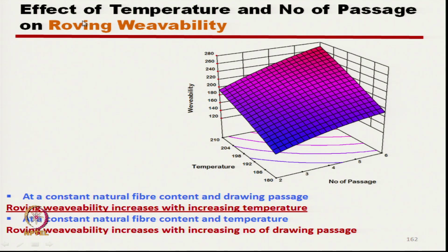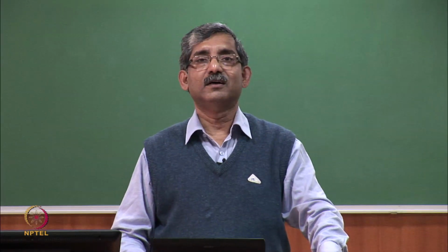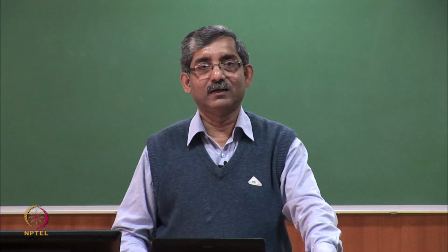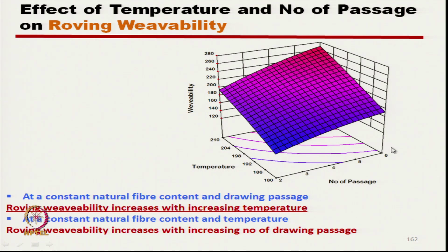And if we see the roving weavability, the effect of temperature and number of passages at constant natural fiber content, say here we have kept the natural fiber content at 60% and at the same number of drawing passages, the weavability increases with the increase in temperature. That means proper binding of natural fibers is there. So, it enhances the strength and thus weavability increases. On the other hand, with the increase in number of passages, we have proper blending and proper binding of the natural fibers. So, weavability also increases here.